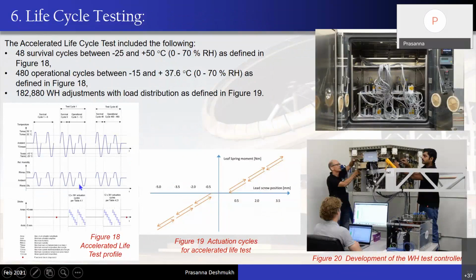And what it includes is basically we had to do testing on these actuators for almost 50 days, which means we are recreating 50 years of testing in 50 days. Hence, it is called accelerated life cycle testing, in which we have to run several survival cycles, several operational cycles, and several warping harness load adjustment cycles. Now, what it means is basically you put this entire system in the environmental chamber, switch it on, and keep observing the output strains at the leaf spring, and change the temperature from -25 to 50 degrees at relative humidity changed parallelly from 0 to 70%.